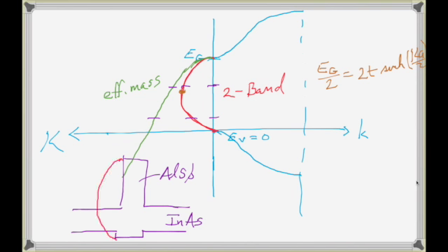Even though I'm an electron coming in here and tunneling through the barrier near the conduction band edge, I'm actually below the midpoint of this wrapping. So as far as the aluminum antimonide is concerned, I'm tunneling through the valence band. I'm below the midpoint here, about down here. So I'm really tunneling through a barrier presented by the valence band, through a point down here.